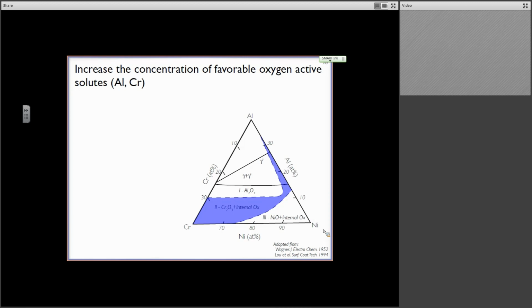So there's similar behaviors for iron-based systems as well. But in this particular case, I'm overlaying the expected oxidation behavior on top of the phase space. So we can see that if we have mostly nickel and there's not a lot of chromium or aluminum, we expect to form a nickel oxide and get internal oxidation, and this would not be desirable.